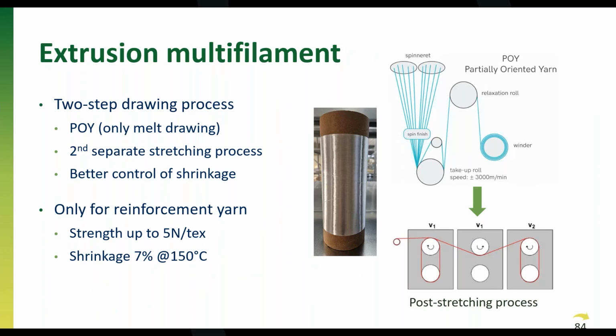ovens this time, not on heated rolls, with which we then have better control of the shrinkage and of the temperature that these yarns get. We only do this for the reinforcement yarn because this is the most important one, also for mechanical properties. And with decoupling, so with the two-step drawing process, the strength also goes up quite high. Up to 5 Newton per tex we can achieve, while it was only 3.5 for the one-step drawing process. So here we far exceed what we need or what the requirements were. And also the shrinkage is heavily decreased to 7% at 150 degrees.